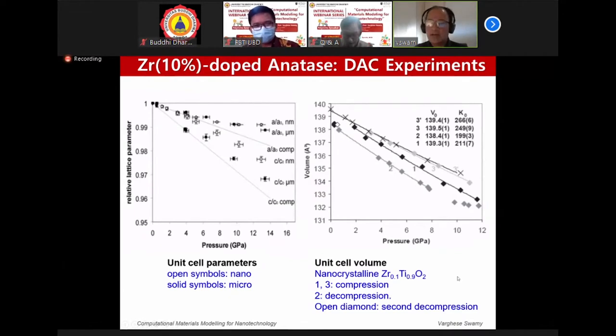To the right, what is shown is, again, the same zirconium-containing anatase, compressed initially. This number one shows the compression. And then you leave it there, the curve breaks here. And when you decompress, that means you release the pressure, it follows a different path and gets here.